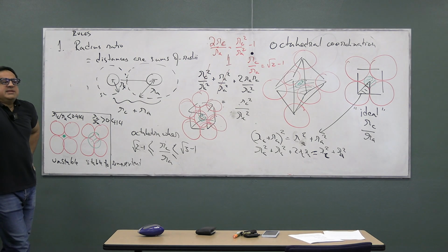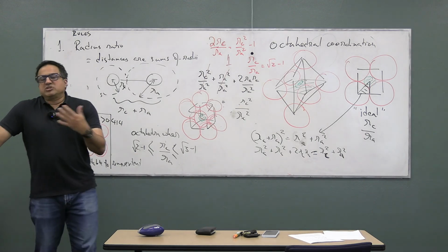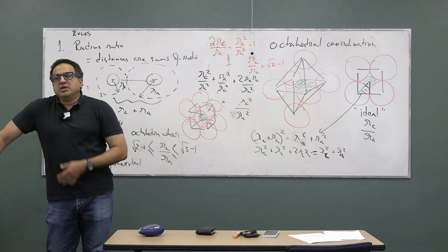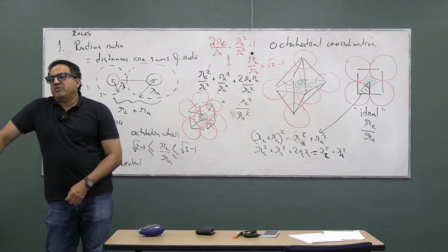How are these radii determined? These radii are what are called empirical radii. Today, the radii that we mostly use come from Shannon, or two people, Shannon and Prewitt, working for the DuPont company. They went through a lot of crystal structures and systematically went through all the atom-atom distances and said, this makes sense for the radii of these different atoms under these different conditions.